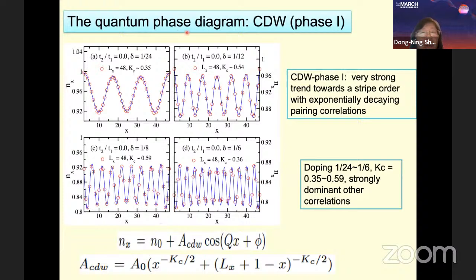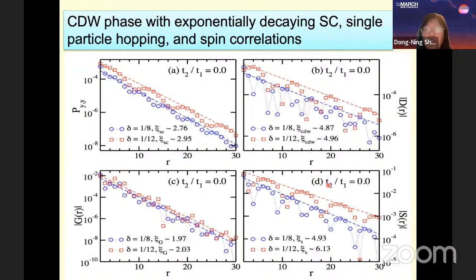For the first quantum phase, the CDW phase, as we vary the doping level from 1 over 24 to 1 over 6, the CDW pattern varies as the stripe period changes. However, within each stripe we always have 4 electrons. The amplitude of the charge density oscillation decays in a power law, because this is essentially a 1D system. The power law decay exponent is very small, around 0.35 to 0.59, which means a very strong quantum order for the charge density.